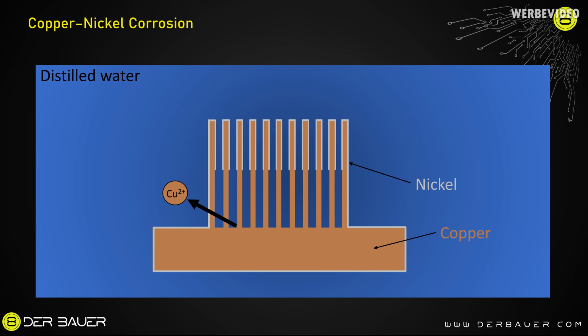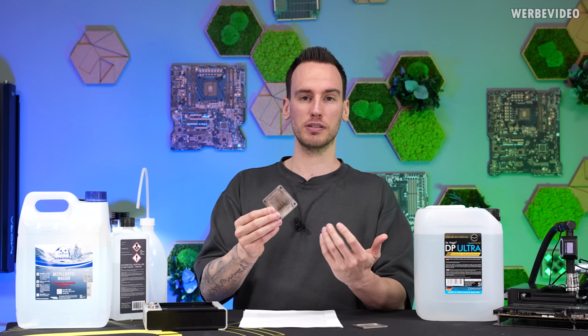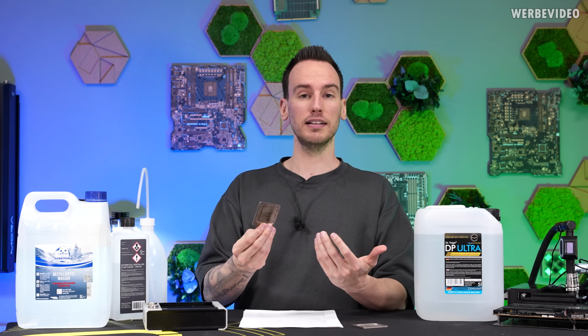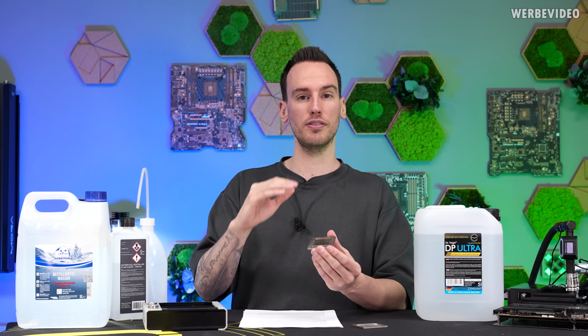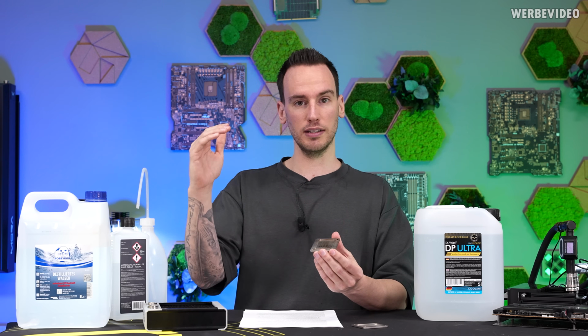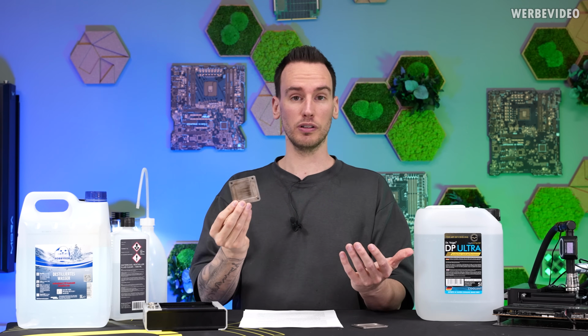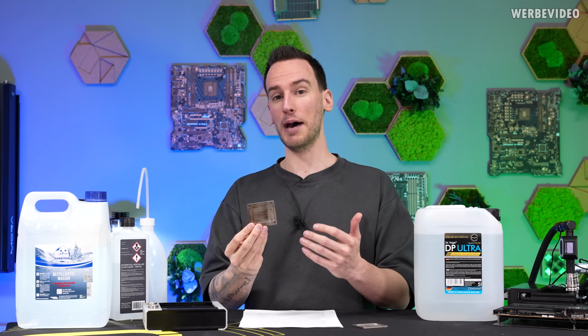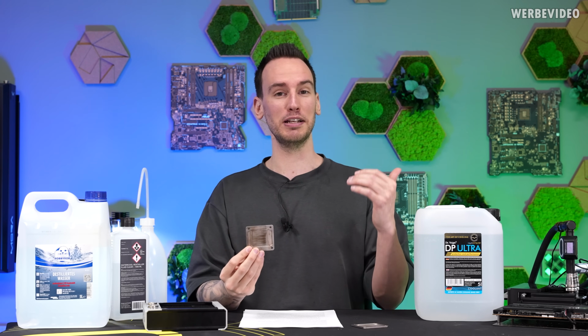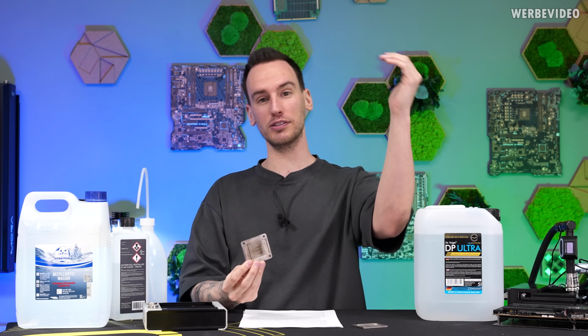Then it takes up the copper ions, the Cu2+ ions, out of the copper. And this is then deposited onto the nickel, because those ions take two electrons from the nickel, and it's basically copper plating itself. From a technical perspective, it's actually not that terrible. It just looks bad. It looks really bad, but it technically isn't really an issue, because it's just a nanometer thin layer of copper that you're depositing on top of the nickel. So at first look, it looks like the nickel was etched away, but that's absolutely not the case. We just deposited a little bit of nanometer thin copper on top of the nickel.